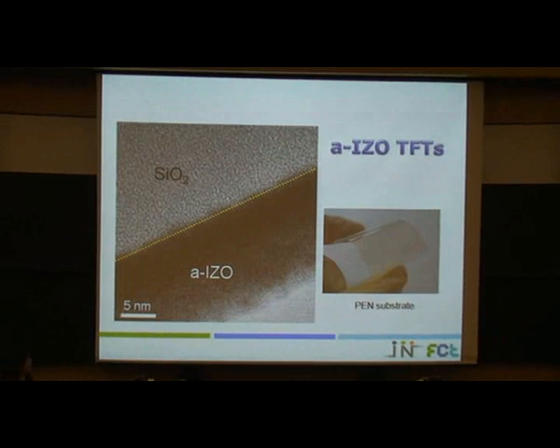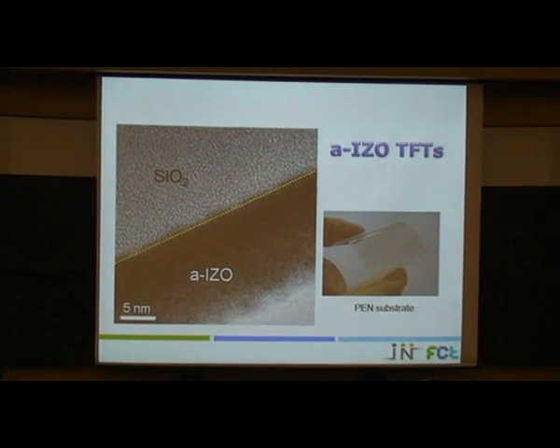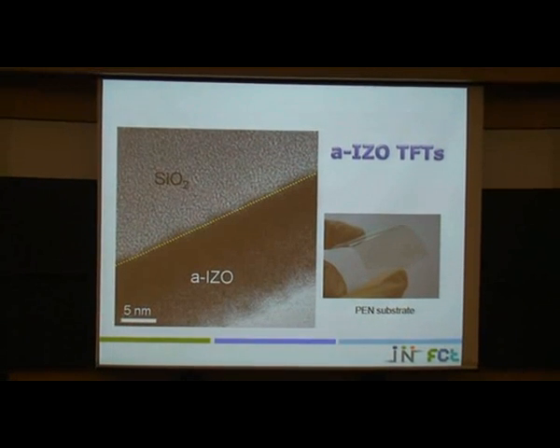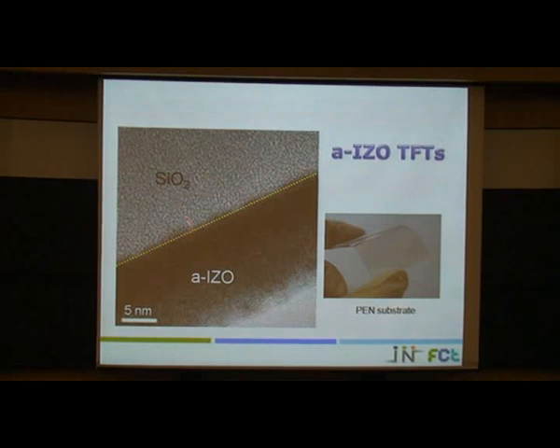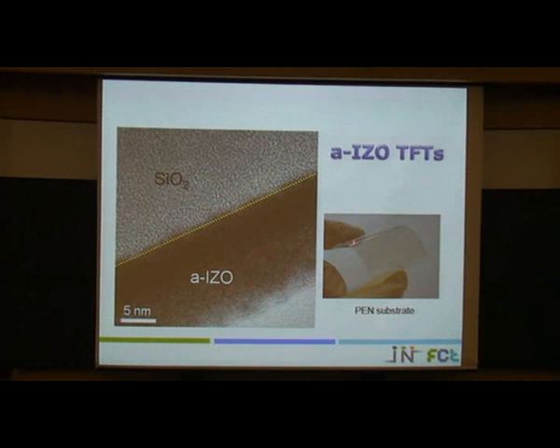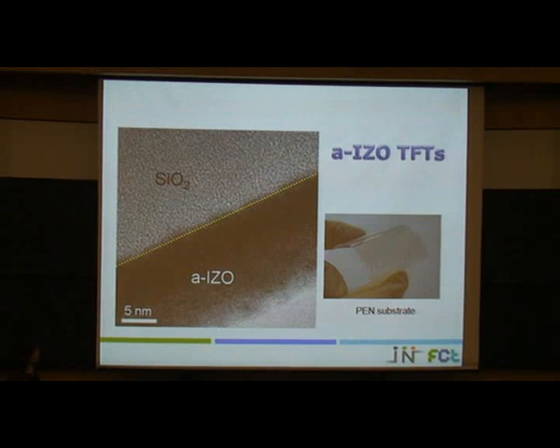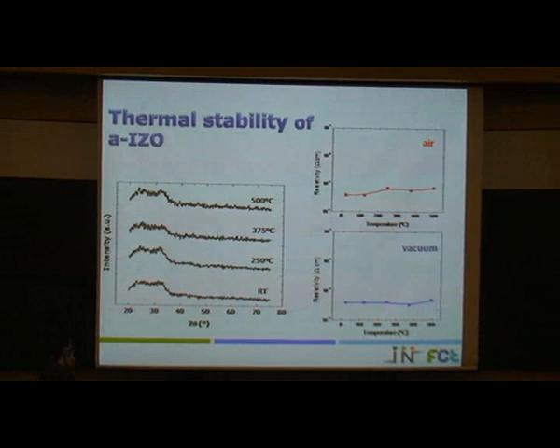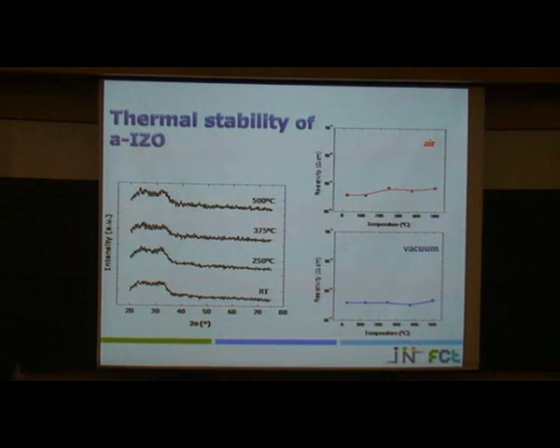This is an example of an indium zinc oxide film deposited on silicon oxide on a wafer, and this is a high resolution TEM cross section image where you cannot see any crystals. So the structure of the material is amorphous. And this is the film deposited on a plastic substrate, just to show that it's possible to do this at room temperature.